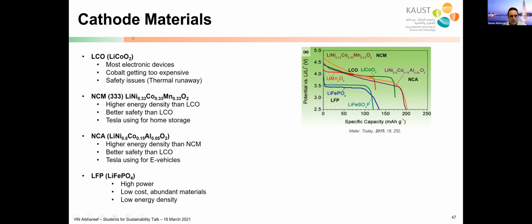So for NCM and NCA, these are alternate cathode materials to lithium cobalt oxide. This top one is what has been used commercially. NCM and NCA are again different ratios of cobalt, nickel, manganese. The NCA has a higher energy density than this one. Tesla is using that in the electric cars, but Tesla is using NCM in the home-based storage because this one is lower energy storage. This is the one that has lower cobalt, so it has the lower cost, so it can be used in the home. And this is the one that has the higher energy density, so it's used for electric vehicles.